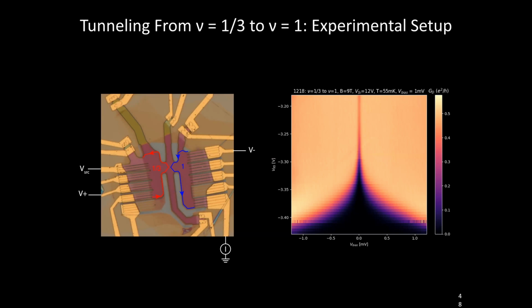Okay, so if you do this, you can study its bias dependence and as a function of how narrow you make this constriction and how high the barrier is between these two. And what you see is that indeed there's a suppression of the conductance at low tunneling energies. So if you don't give the electrons enough energy, they don't go in. That's what you expect to see for a chiral Luttinger liquid. You can't put electrons into this chiral Luttinger liquid at low energy.